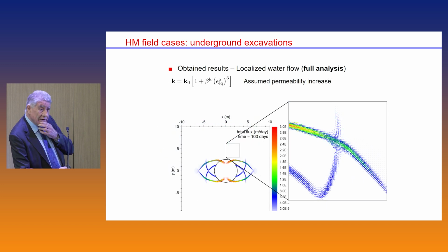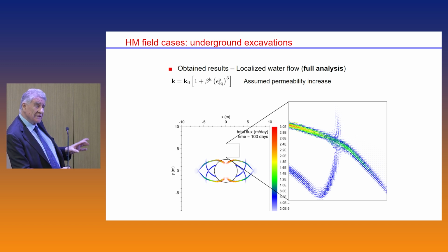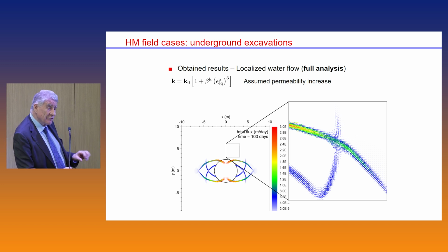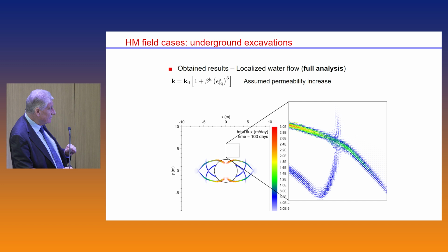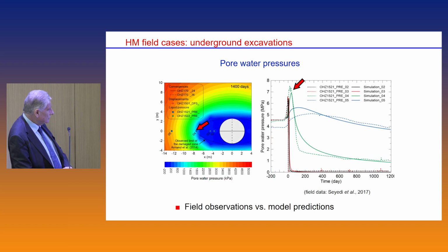There are more benefits from this analysis. For instance, looking at the flow of water. The flow of water gets concentrated in the localized zone just because we have this increase of permeability with plastic strains. These localized zones actually concentrate the plastic strains, and that's where the flow occurs, which means that the region around, at least the horizontal one around the opening, is relatively well drained, or better drained due to these localized zones. And that explains some observations.